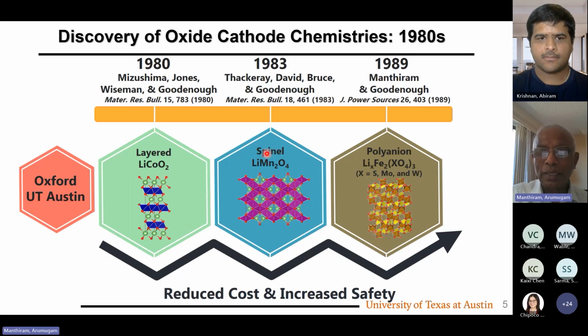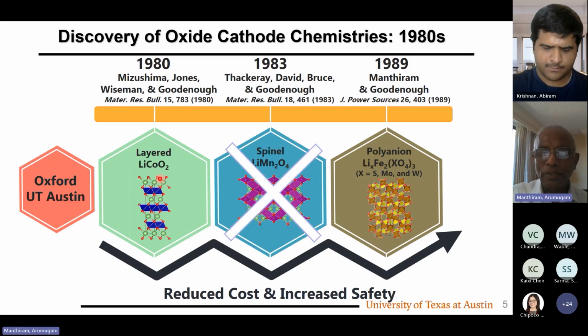All the cathode technology we use is based on this basic concept. Right now, layered oxide is heavily used, but because of the cost, there is more interest to go towards these kinds of compounds, or lithium iron phosphate, LiFePO4, that belongs to the same kind of polyanion.